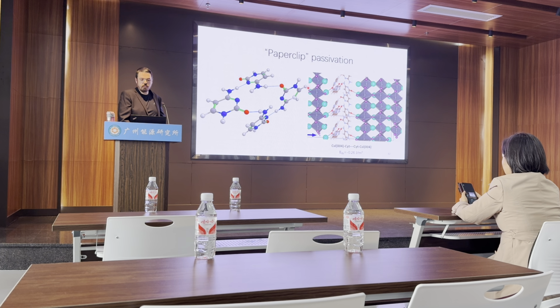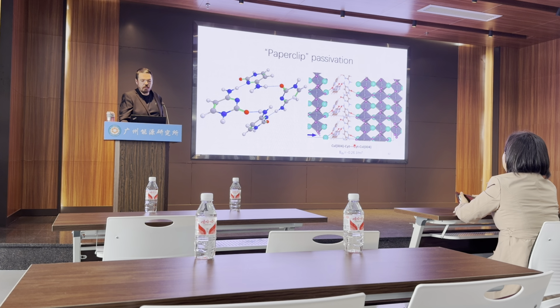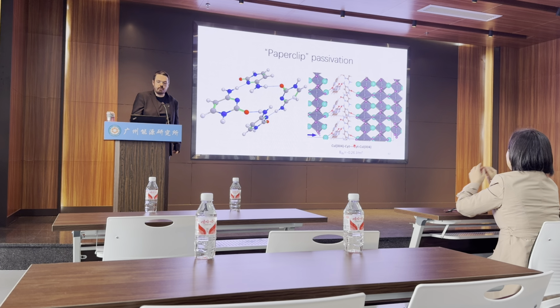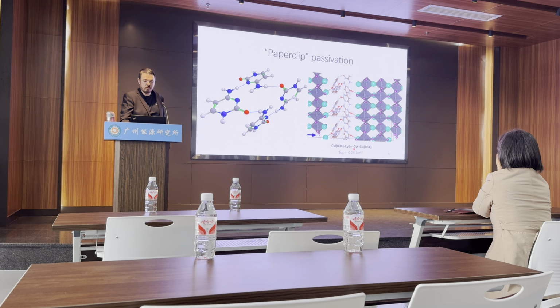The really cool thing is we thought about it and proposed something theoretically: we could make this kind of paper clip of 2 dimers of cytosine. They make this paper clip that can actually grab hold of 2 perovskite grains and hold them together. And when we calculate the interfacial binding energy, it's very strong, because remember the 2D phases based on PEA are like 3 or 4 times smaller than this. So this will create a very strong binding between the grains. That's interesting. So that's something we need to investigate.